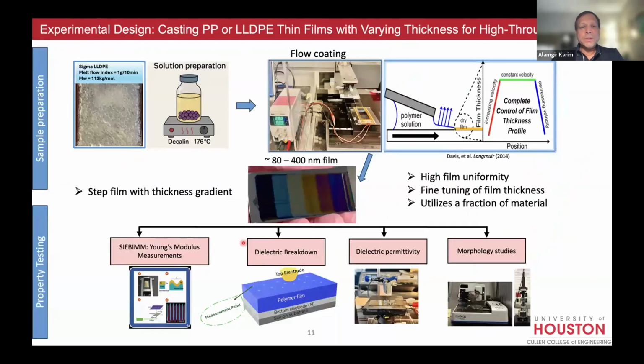All right, so now coming to what we do, I'm going to show you results in two categories, polypropylene and polyethylene, okay? So we cast these films from heated Decalin solution. It dissolves well. You wait half an hour, 1 hour, and it'll be a proper polymer solution, whether it's polyethylene or polypropylene. You can also take metaxylene or orthoxylene, heat it up to 140, but Decalin seems to work better.